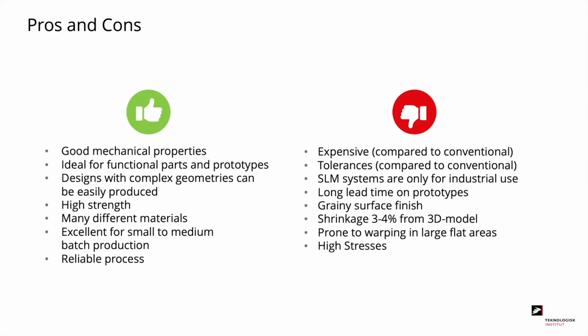Some of the downsides: it is an expensive process compared to conventional manufacturing. Tolerances are not as good as conventional manufacturing such as CNC machining. SLM systems are mainly for industrial use, and there can be somewhat long lead times on prototypes. The surface can be grainy. It has a shrinkage of 3 to 4%, but that can be compensated for. It is prone to warping in large flat areas. And finally, we have high stresses, and this is why we have heat treatment afterwards.